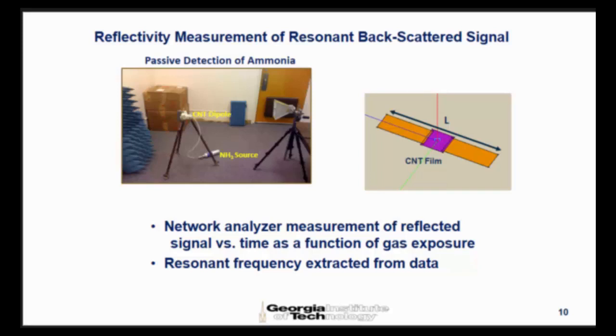So what I do is I put this on a pedestal and I have a horn antenna connected to a network analyzer. I measure the reflectivity of this sample using the received signal. So I'm basically measuring S11 of this horn antenna. And from there, I can look at the resonant frequency shift as a function of gas detection. You can see a small gas cylinder there, which is exposing the sensor.